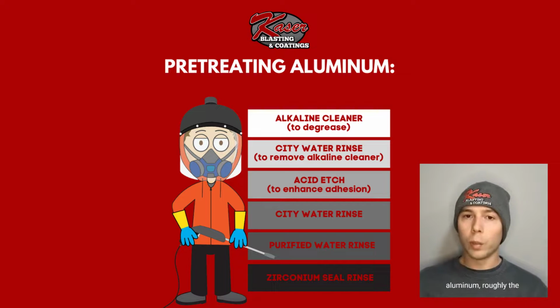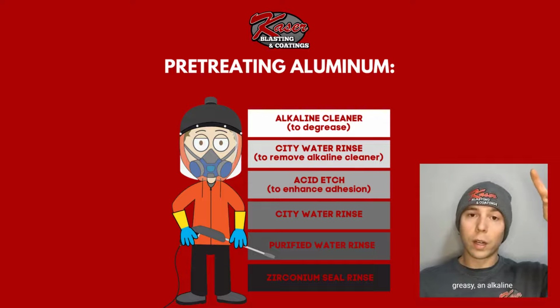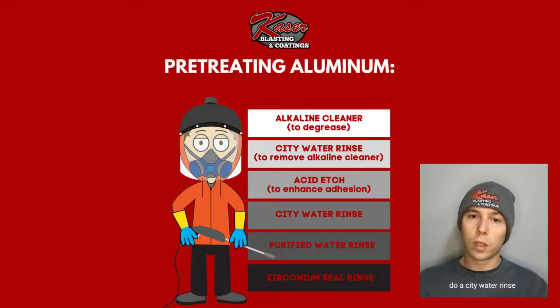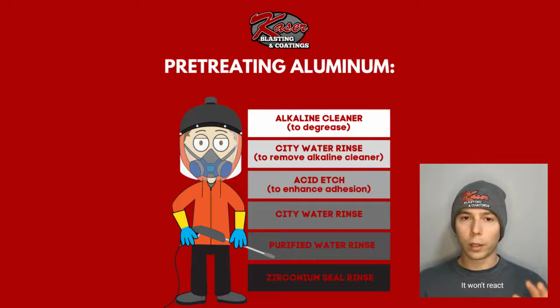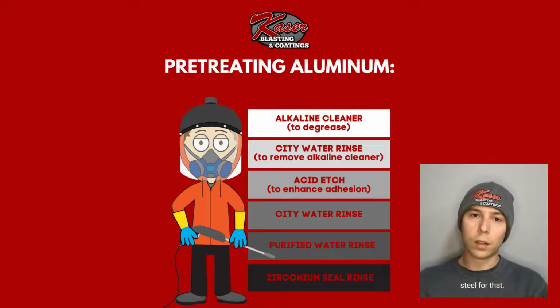For pre-treating aluminum, roughly the same kind of steps that we would do for steel, but we just have some different chemicals. If the aluminum is very greasy, an alkaline cleaner is going to really help cut through that, so we could use that for our first stage. Then we're going to do a city water rinse again to rinse away the alkaline cleaner and the grease and oils. On aluminum, we're not going to use phosphate. It won't react with aluminum. It won't create a coating on aluminum. You have to have steel for that.